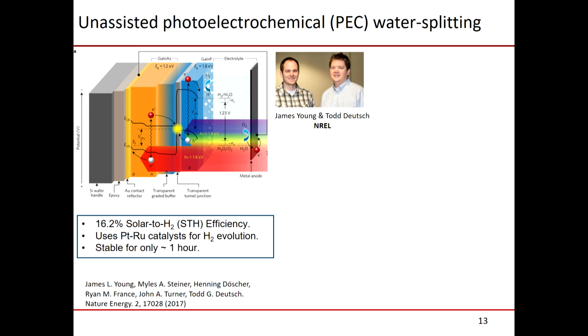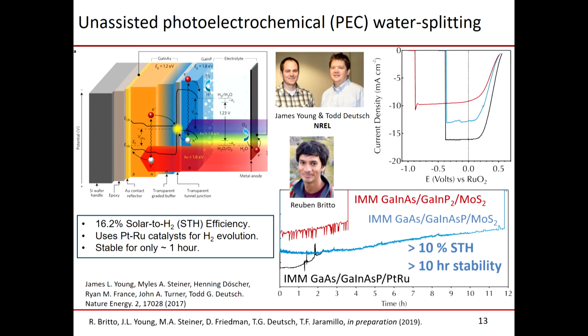Well, these materials that I'm describing, these sulfides, actually turn out to be pretty solid materials as well that are very stable in those types of environments. So my student Ruben started taking a lot of these tandem systems that were coming from NREL, fabbed by the team out there, and layering MoS2 on them, demonstrating greater than 10 hour stability, a factor of 10 better than the platinum ruthenium, while still maintaining very high solar to hydrogen efficiency, about 10%. Now, this might not seem very exciting to you, 10 hours. I just showed you almost 1,800 hours.